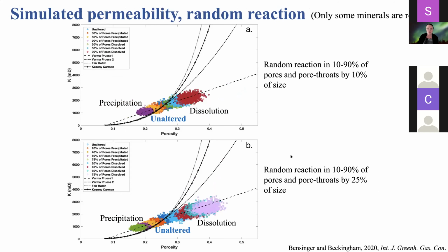Now if we look at the random reaction scenario, so this is basically if only some of your minerals are going to be reactive. And we vary the fraction of reactive minerals from 10 to 90%, and then the extent that they were altered by the reactions. So looking at 10% alteration on the top and 25% alteration on the bottom. And you'll notice that this looks really similar to one of our uniform reaction scenarios, where dissolution results in an increase in porosity and permeability, and precipitation, a decrease in porosity and permeability. And these are both captured well by the Verma-Pruess equation.